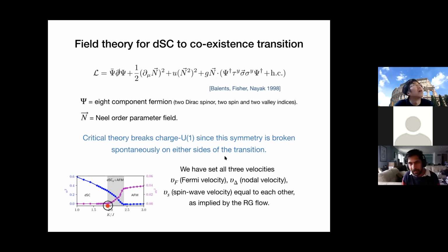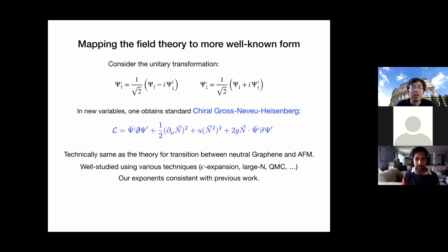Then you start doing RG, and we noticed that somehow the RG looked identical to the conventional Gross-Neveu fixed point, or the Gross-Neveu-Heisenberg. For a while, at least for a day, we were a bit confused about why that was happening. Then we noticed there's an interesting transformation you can do. You can do a rotation. It is not just the usual particle rotation. It employs the fact that the free Dirac fermion has O(4) symmetry because of the Majorana representation, and you map it to the conventional Gross-Neveu-Heisenberg fixed point. Then all the exponents based on large N, epsilon expansion, and all the other numerics match the exponents I showed you earlier. At least it's consistent with them.